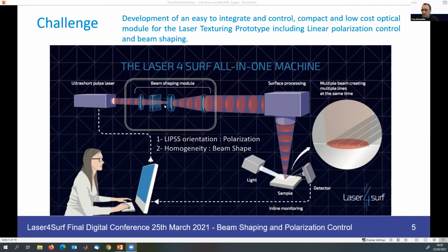And in between the laser and the scanner, there is a beam shaping module that is needed to convert the Gaussian beam into a top hat beam, mainly to get something really homogeneous on the sample, and also to orientate the polarization. And as I said before, it has to be connected with all the elements of the machine. So you have to be able to synchronize, for instance, the rotation of the polarization with the scanner if you want to make different orientations in function of the path of the beam.